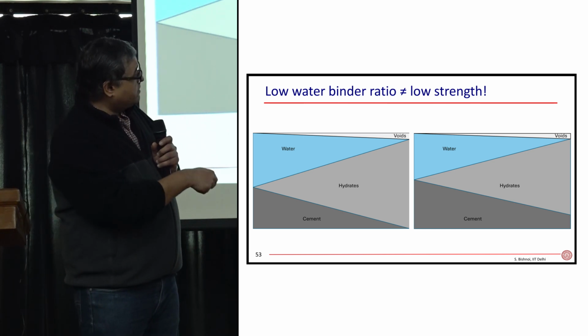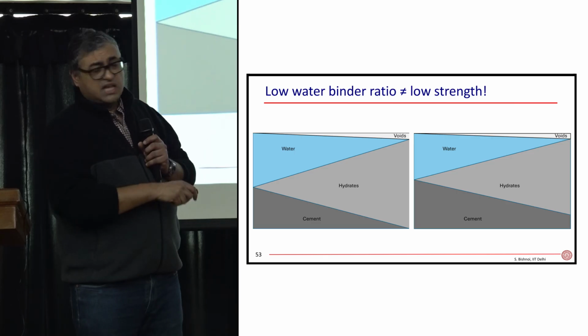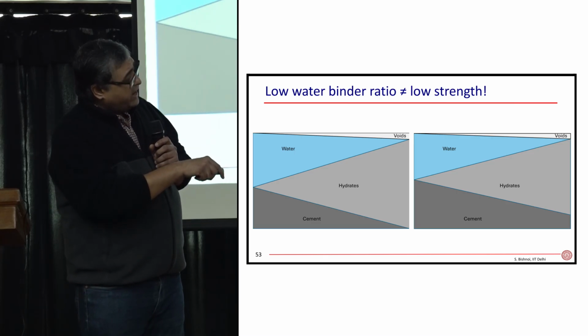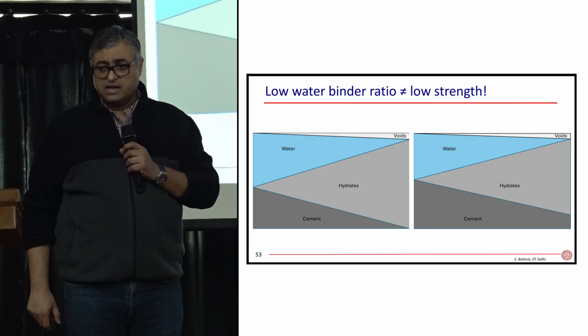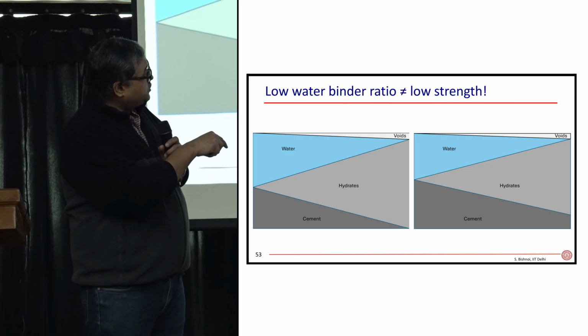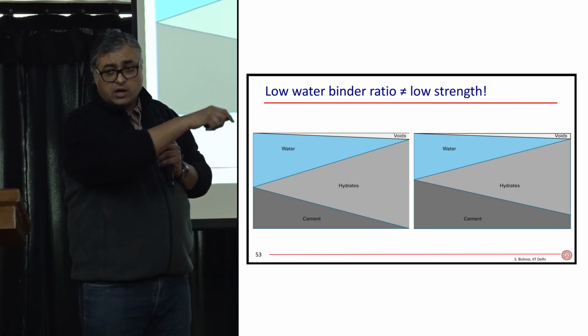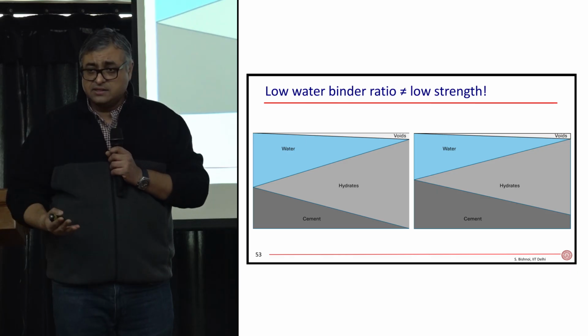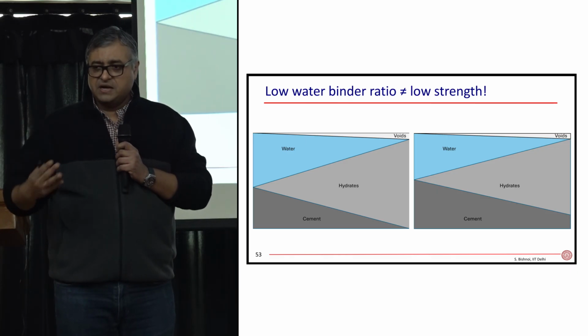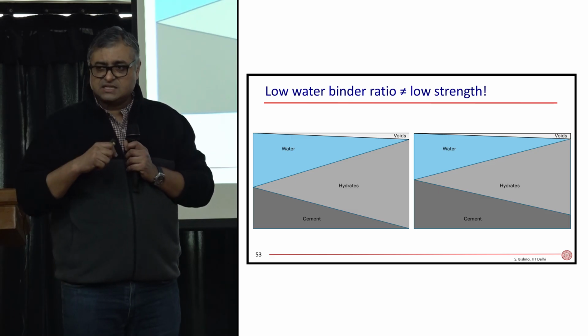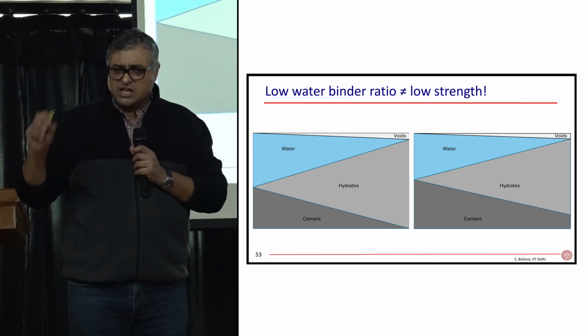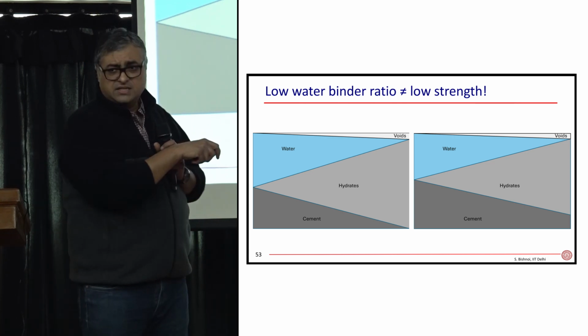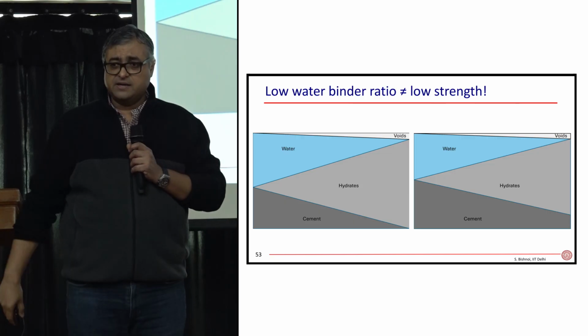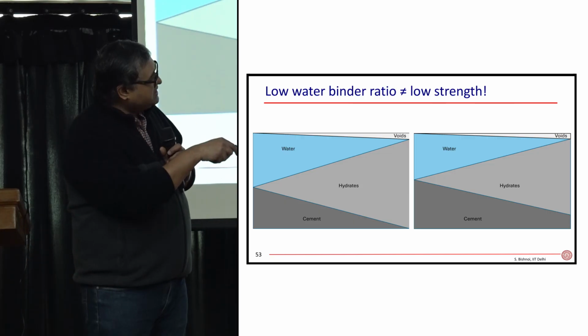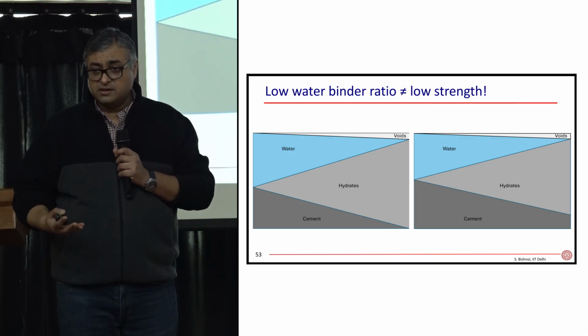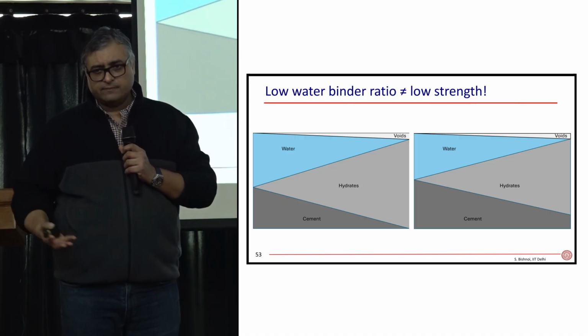Whereas if you have a lower water binder ratio, you have more cement. Even after all the water is finished, you end up leaving some cement behind. In this case, you started with more solids and end up with more solids, less pores, higher strength, lower porosity, lower permeability, better durability as well. There are some voids left inside the concrete. If I cure my concrete, put water from outside to fill these voids, maybe that water can react with the cement left behind, and if it does, it will also fill some of those voids. The concrete will become even stronger—there is some use of curing in that case.